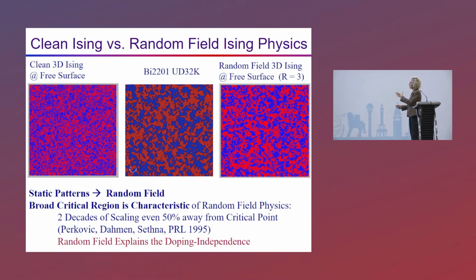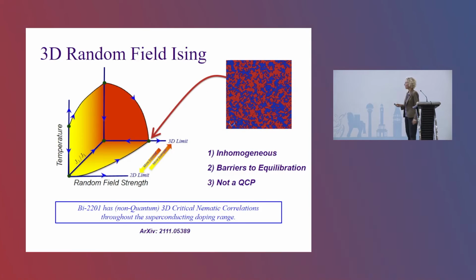And so the fact that these patterns seen in an experiment are static is another indicator that it's random field physics, because the barriers to equilibration go sky high in random field models. Rather than the usual critical slowing down, they have extreme critical slowing down. The time scales for equilibration blow up exponentially as you approach the critical point. So, our conclusion here is that BSCCO has 3D critical nematic correlations throughout the superconducting doping range. And there are large barriers to equilibration, inhomogeneity there. This is the fixed point that this pattern formation is near.